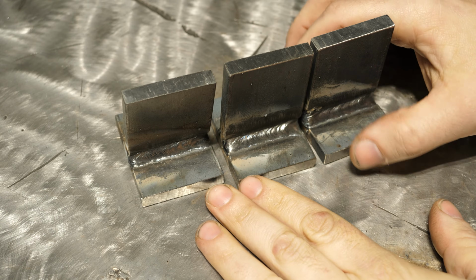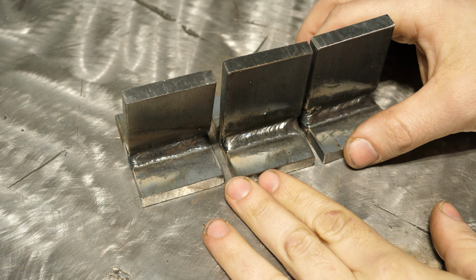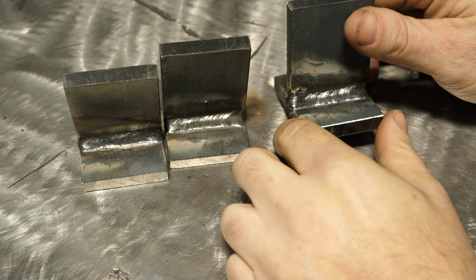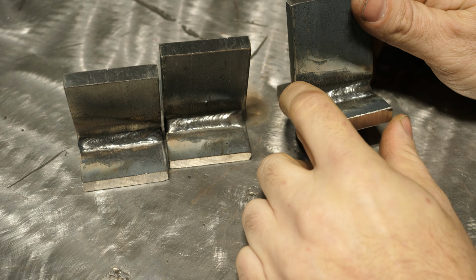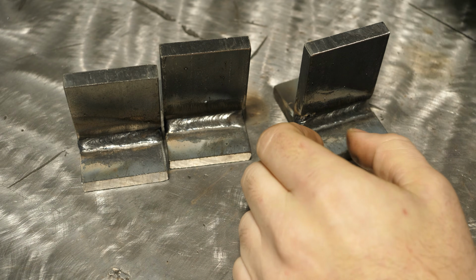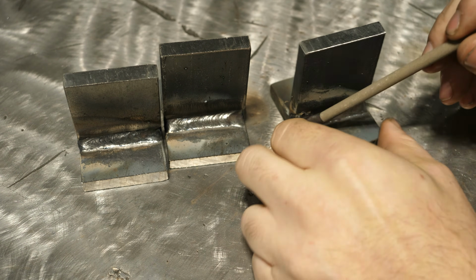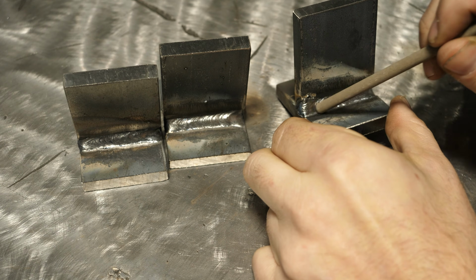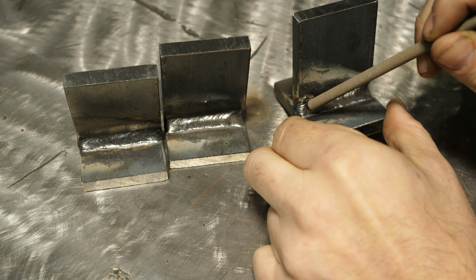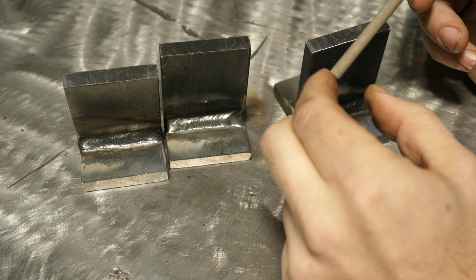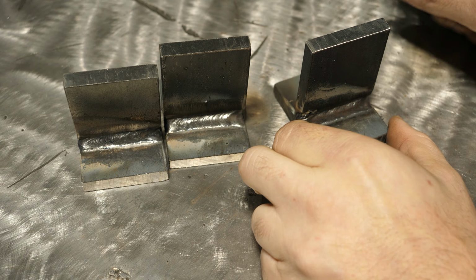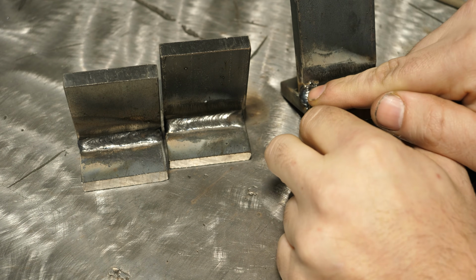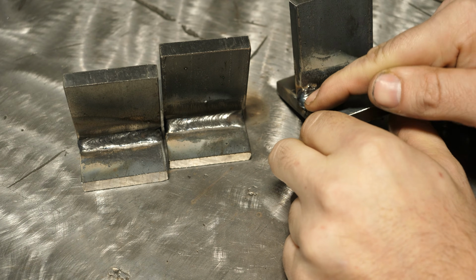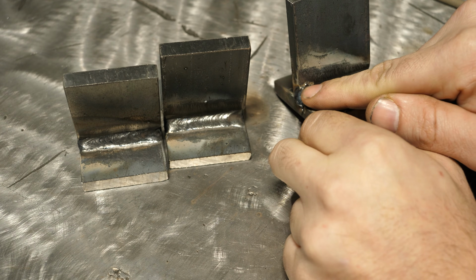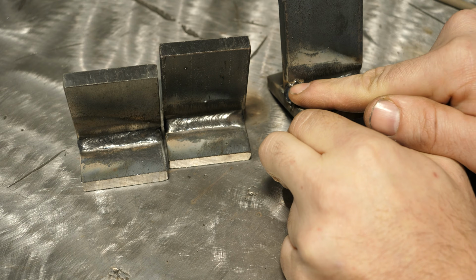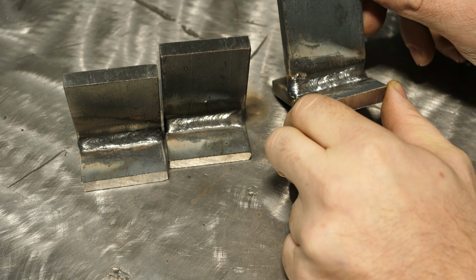So I got all of these welded up, and guess what? Mistakes were made. The first one that I welded had a difficult time starting the rod, because the flux on this is so wide, trying to strike it down in the corner was almost impossible because the rod tip never contacted the metal. So like an idiot, I tried to strike it a little bit higher and bring it down. Well, I had a bad start, and look, arc strike. That's generally an undesirable characteristic.